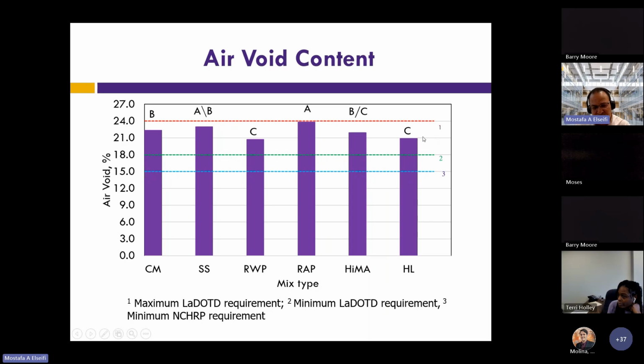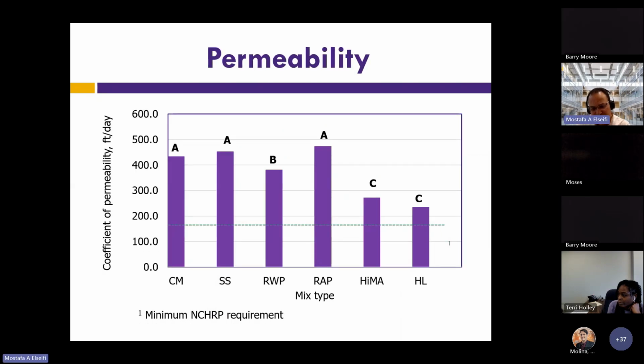as it is important to do because you want your mixes to be comparable. If we look at the permeability, the permeability is directly related to the air void. You can see here that HiMA and hydrated lime had the lowest permeability, but it's still higher than the minimum requirement. And for the other mixes, CM, steel slag, and RAP were statistically equivalent. And the recycled waste plastic also fell between the two groups.